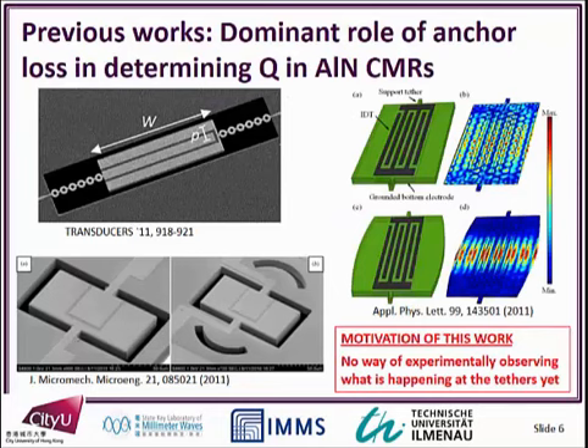This has been seen in quite a few works, and people try to find ways of getting around it, increasing Q and reducing anchor loss. For example, people have tried to shape the resonators in order to confine the energy to the center, and that's been found to actually raise the Q. That would be one more data point to say that anchor loss matters. Or, for example, putting acoustic reflectors at the end that reflect energy back into the resonator. Or using other kinds of novel structures like phononic crystals that create an acoustic band gap, and that also acts to reflect the energy back out of these tethers into the resonator itself.